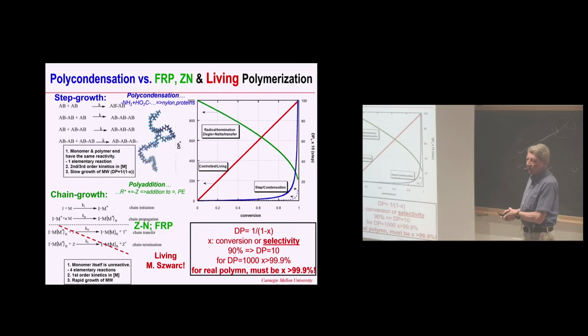So in order to get molecular weight at a lower conversion, you can think about a chain growth reactions. In a chain growth process, monomer does not react with monomer. Monomer needs to be initiated by some kind of an initiator. It can be acid, base, organometallic species, or free radical. And then after generation of the first active center, it reacts very quickly with another monomer. Frequency of monomer addition may be in a range of milliseconds, sometimes even microseconds. So within 1 second time, you get huge molecular weight, degrees of polymerization, 1,000 or sometimes 100,000 even. And then molecular weight typically drops with conversion because you have chain breaking reaction, transfer and termination. So it is very difficult somehow to dial exact molecular weight because you have many elementary reactions.